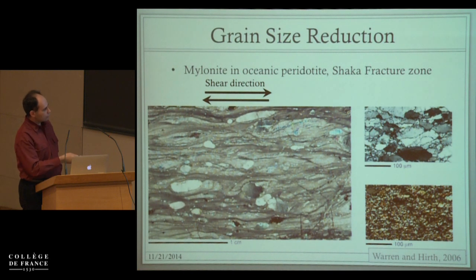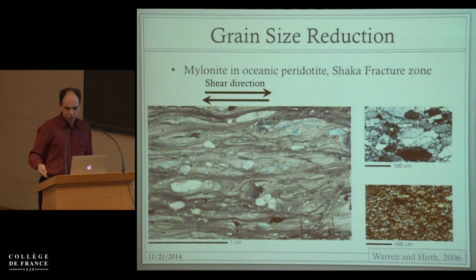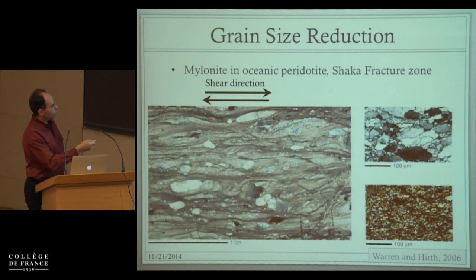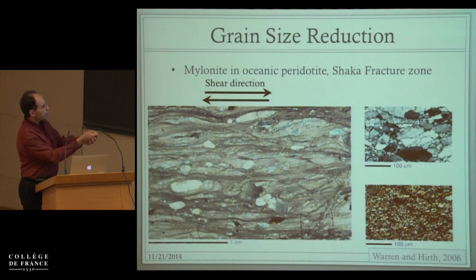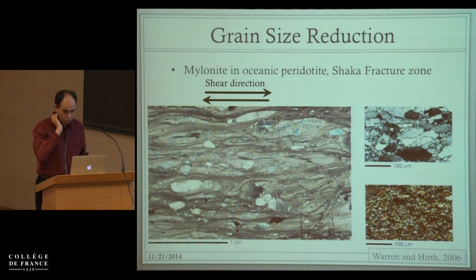It turns out that for the mantle rheology, the rheology is probably not nonlinear enough to make a big effect just from the layering itself. But what you can see is an intense reduction of grain size. The original grain size is probably of the order of a few millimeters, like we see in those remnant grains there, and seen in undeformed peridotites in other places. But inside these deformation bands, you zoom in and you find just a few microns in grain size. So there's been an intense grain size reduction.